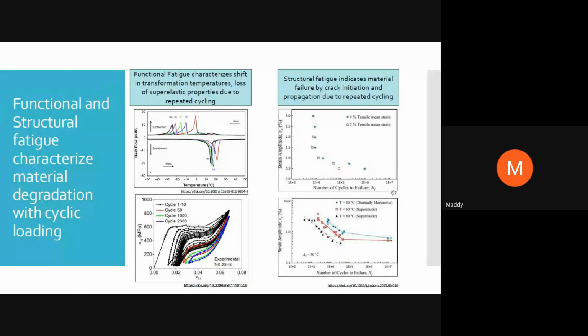So what it implies is that as you increase the number of cycles, the change in the response is going to be more or less stabilized. The same thing happens for heating as well as for stress-induced transformation. And so this is something that the designers are aware of, and they see how they can get this stability, what kind of pre-strain they have to introduce, or what kind of cycling has to be done on the material. So they take into account all these things so that they can get a reliable performance of the material for that specific application.